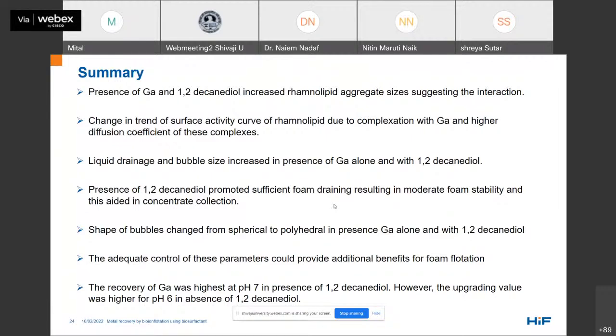Adequate control of these parameters could provide us additional benefits for foam flotation with respect to recovery and upgrading of our metal ions. And these experiments show that gallium recovery was highest at pH 7, but the upgrading value was higher at pH 6.